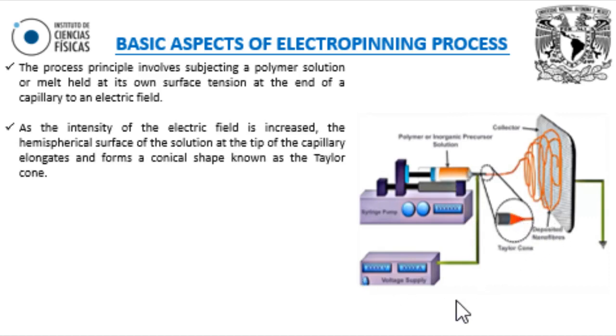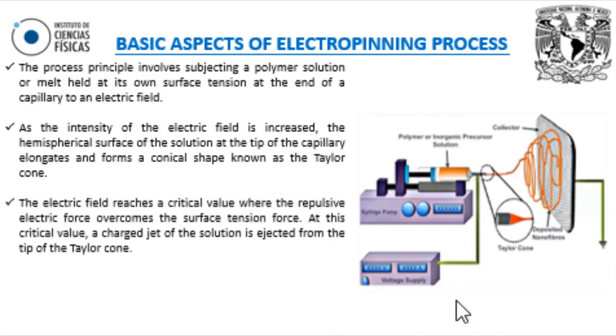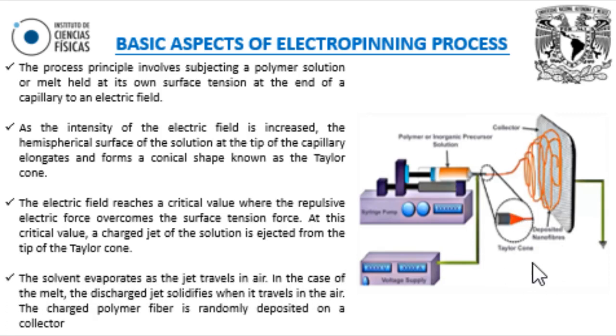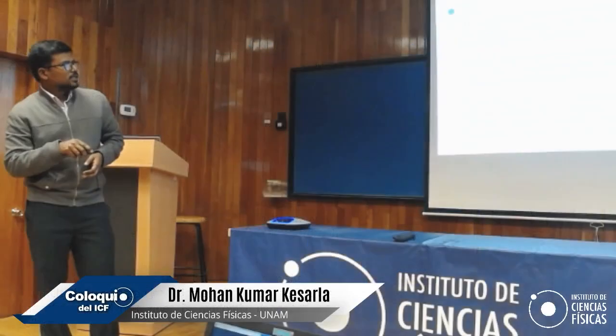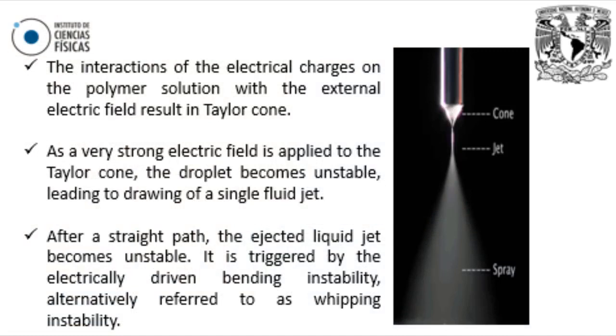Once again, the electric field reaches the critical point. What will happen? The repulsive electric forces overcome the surface tension forces, and this is the critical point where the charged jet is ejected from the tip, and it forms a fiber. There are different regions in this zone. See here, this is the Taylor cone I am talking about, and this is the charged polymer coming out of the jet.